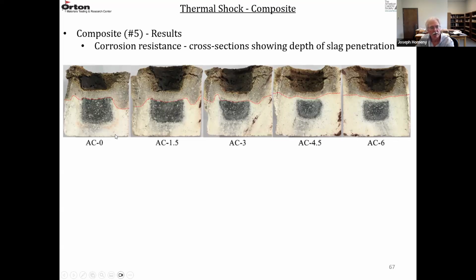So these are the vertical cross sections of the cylinders. So you can see where the hole was in the top of each of the cylinders. That's where the slag was placed. So this was done in an air environment. So you see a decarburized zone around all of these cylinders, and the black area is the remaining carbon that's not been oxidized. And then this darker gray area, gray yellow type area outlined with this dotted line is the slag penetration.